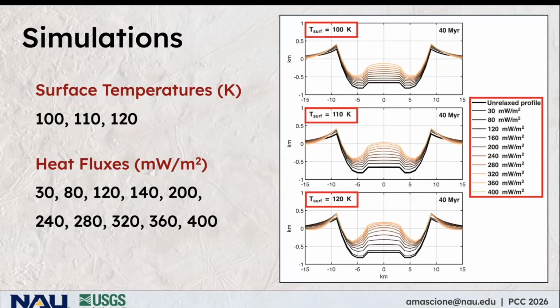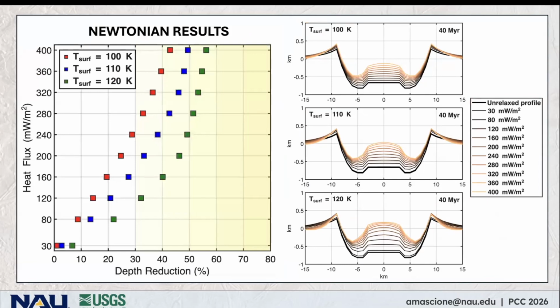Now I'll start with the results of our Newtonian simulations. As expected, relaxation fraction increases with surface temperature and heat flux. Interestingly though, we saw limited to moderate depth reduction within 40 million years. This figure shows quantitatively how much relaxation we saw in each of these simulations.